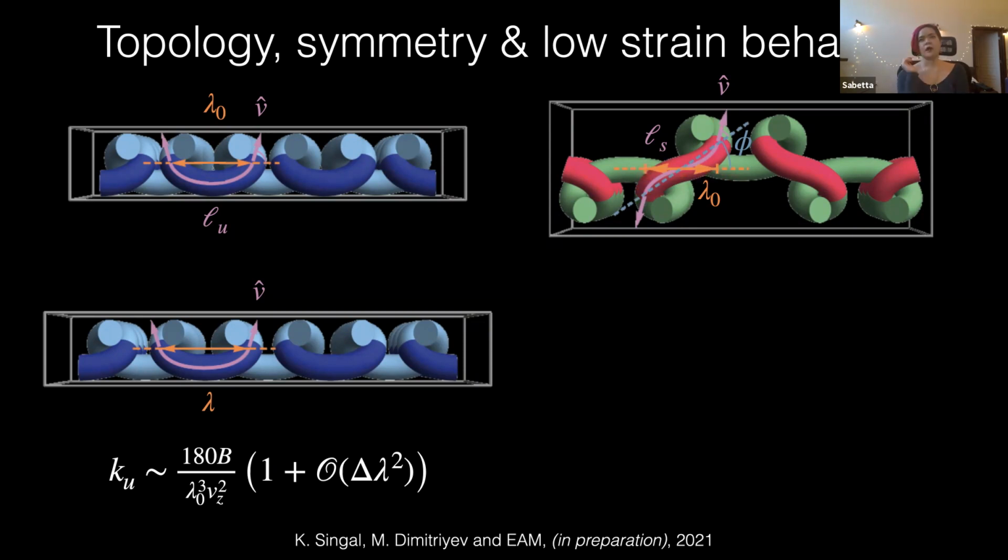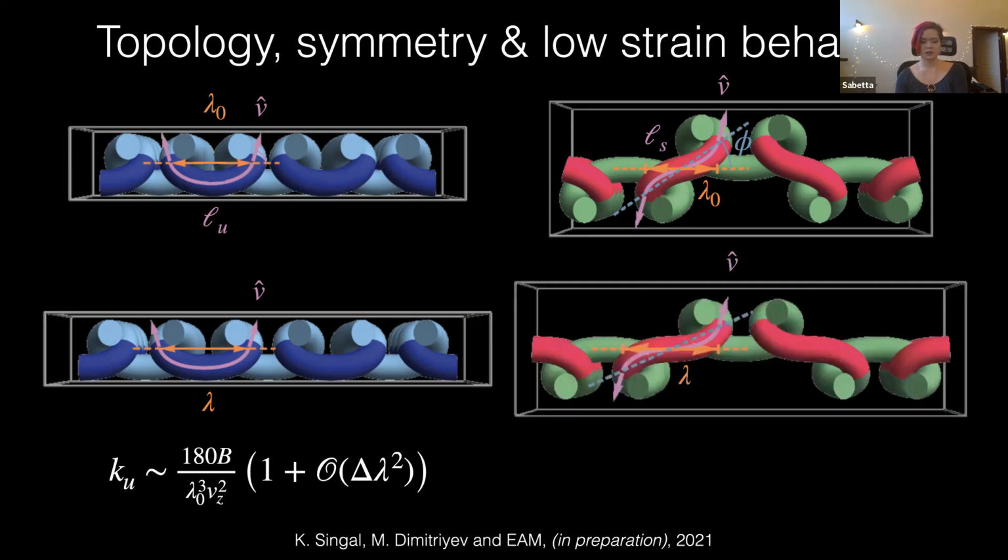And then what happens here is that there's actually a mode that lets us extend lambda naught without introducing much, if any, energy into the rest of the piece. And that's merely by rotating it. So I can take these points and rigidly rotate them a little bit, and that's going to extend lambda naught, but not really change the elasticity of this region. And so this is what that looks like after extension.